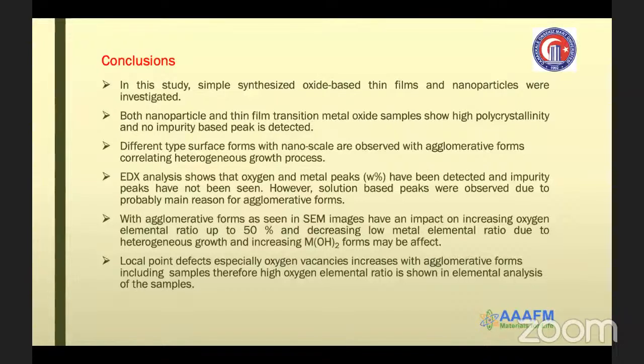However, solution-based peaks were observed, which is probably the main reason for agglomerative forms. Agglomerative forms, as seen in SEM images, have an impact on the increase of oxygen elemental ratio up to 50% and decreasing metal elemental ratio, which causes heterogeneous growth, and increasing hydroxyl metal forms may be affected. And finally, local point defects, especially oxygen vacancies, increase with agglomerative forms, including samples. Therefore, high oxygen elemental ratio is shown in elemental analysis of the samples. Thank you for listening.